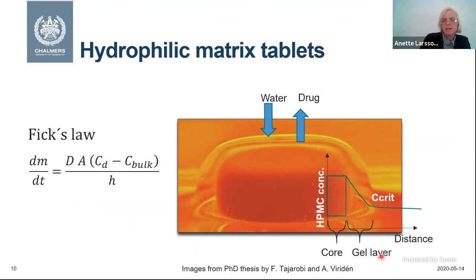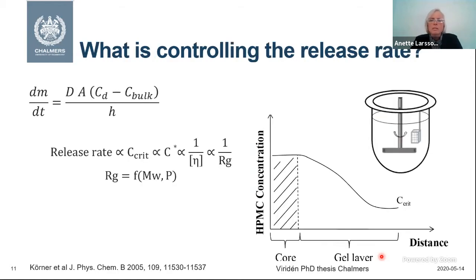So we take this now, we have the gel layer here, and our group was the first group that could demonstrate that we have a critical concentration here on the surface of the gel. The drug release depends on this critical concentration, which we could show was proportional to the overlap concentration.